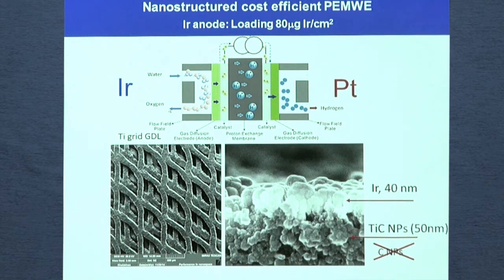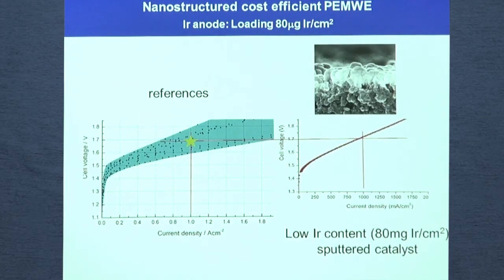Of course, the GDL should also be replaced by something more stable. In that case, the results I will show here were obtained by depositing titanium carbide on titanium mesh. And you can see that by coating the substrate with 80 micrograms of iridium per square centimeter, which is again a much lower value than in the case of the state-of-the-art catalyst, we are somewhere in between these two borders. This is the performance we have.